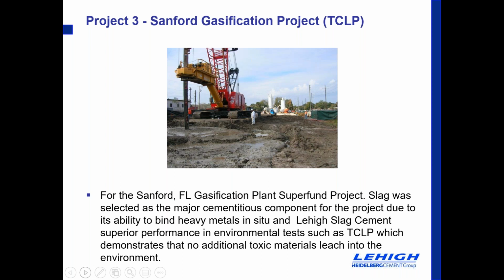The proof in the pudding, of course, is the test wells around the project site, proving that the lowered permeability of this particular mixture was keeping the target heavy metals tied up. So you can see the tool in the distance, you can see the plant there. That is a slag silo and a Portland cement silo. Next, please.